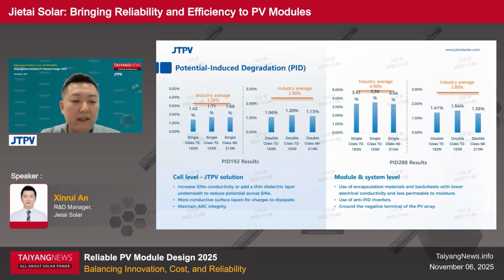The major PID type of concern for TOPCon modules is the PIDp. On the cell level, there are a range of measures to counter it. For example, we can use higher refractive index silicon nitride with higher conductivity, or add a very thin dielectric layer such as silicon dioxide underneath the nitride to reduce the potential across the silicon nitride layer. And some of these measures are well aligned with reducing UV.